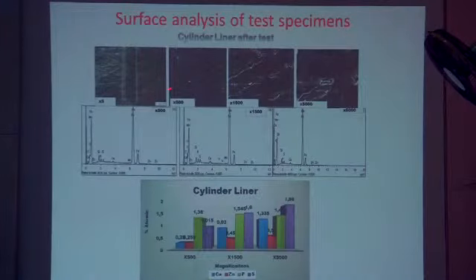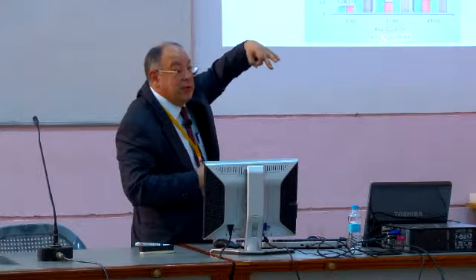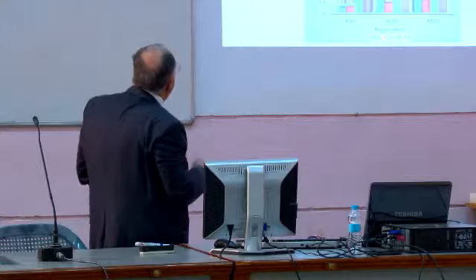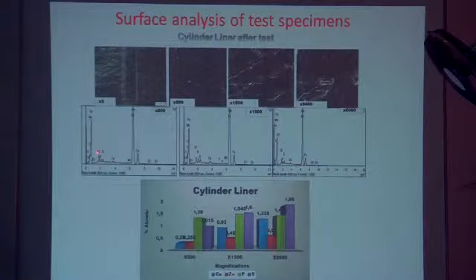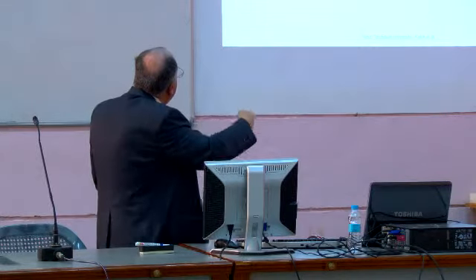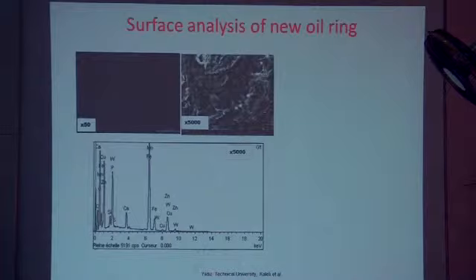This is the cylinder liner after the test, carried out with the oil ring coated by zinc phosphate. And it's very interesting - on the cylinder liner we found it full of additives on the surface. But on the oil ring also, that's very interesting - after the test, the amount of additives was also high.